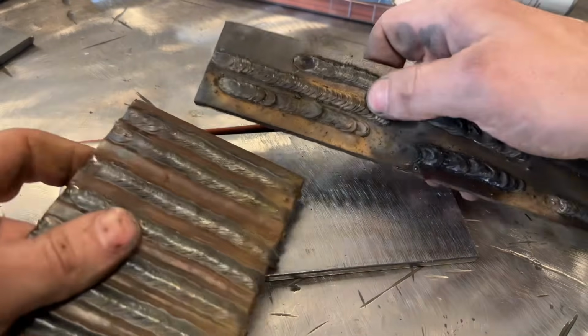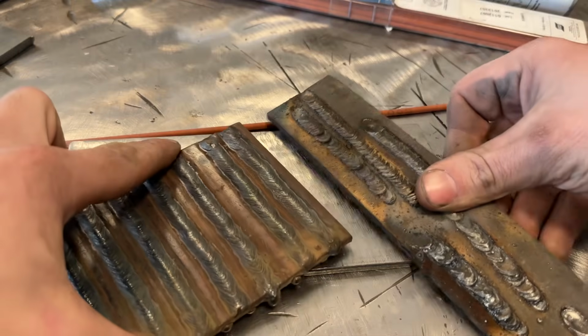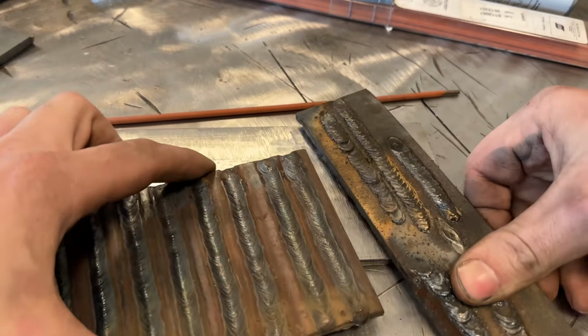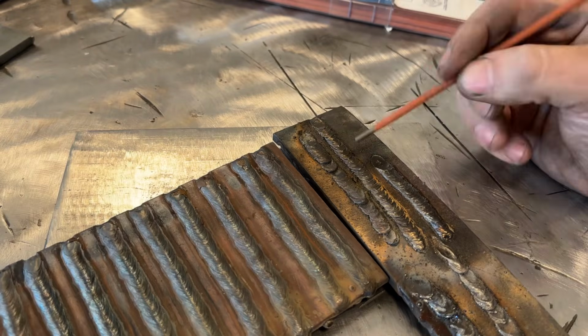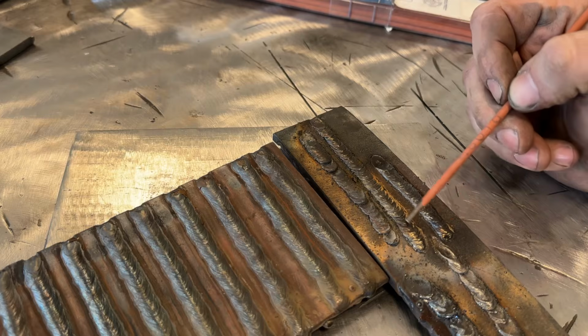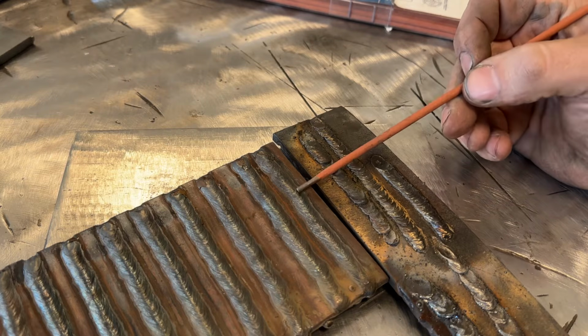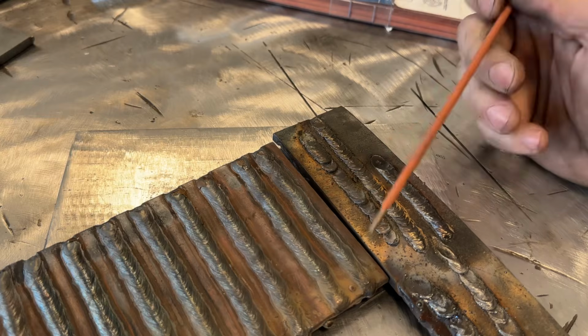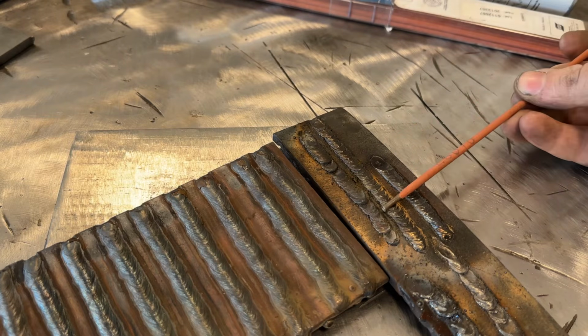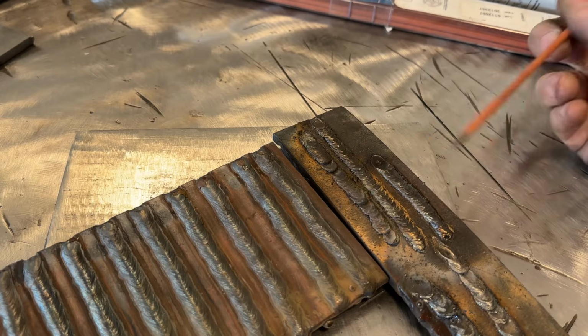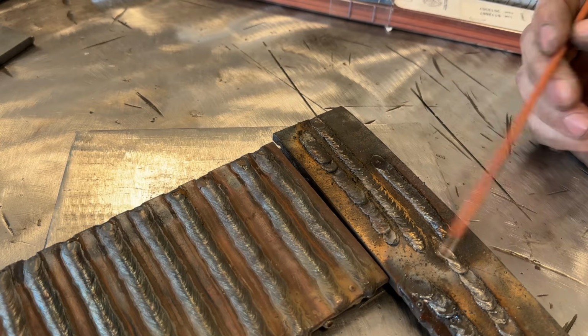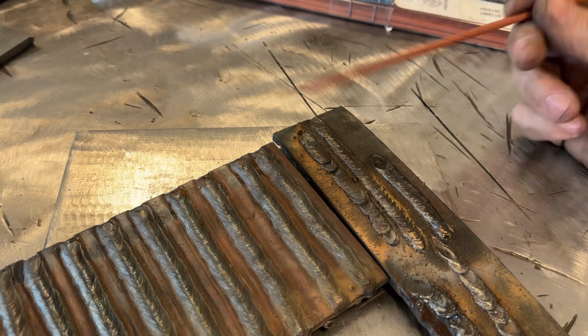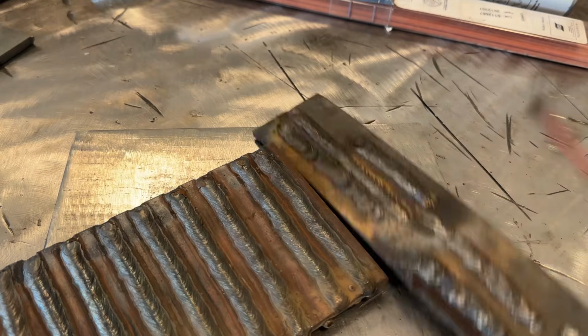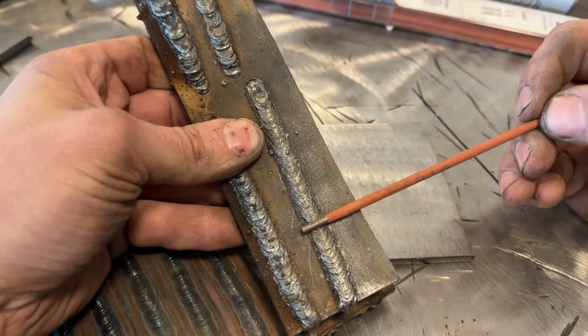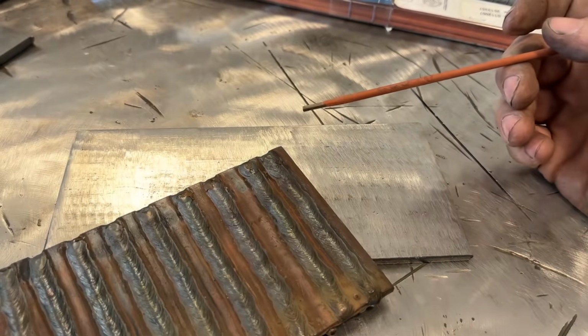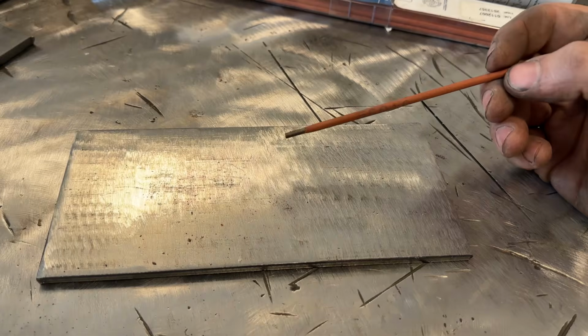Apologies in advance, this stuff isn't the cleanest. If you look here, and I'll try and get this positioned, that'll have to do. This was done with 1/8-inch 6010 rod, I believe. This is 1/8-inch 7018 at varying amperages. You can see, and I'll just lay this rod here, it's pretty much the same width as that. It's very easy: if you try and travel as fast as 7018, your weld with 6010 is going to neck down even narrower than this part right here. So you want to run your travel speed forward pretty slow with 6010.